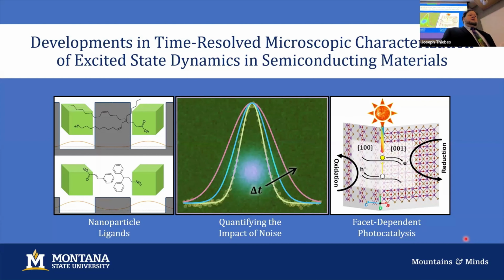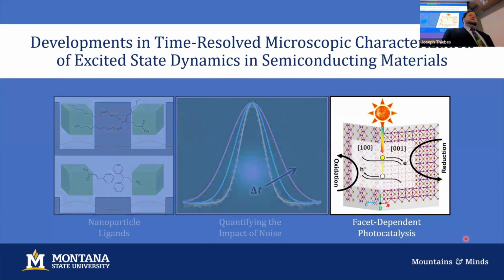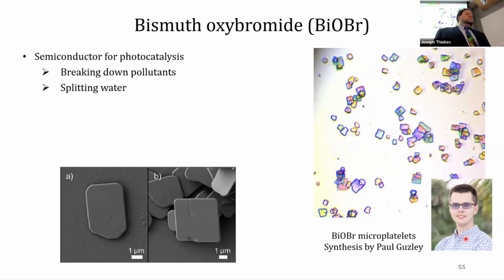So that brings me to my third topic, which is the facet-dependent photocatalysis that we see in this new photocatalyst material, the bismuth oxyhalides. In particular, the one that we look at is bismuth oxybromide. Paul Guzley helped us, and he synthesized these and did this SEM, did a terrific job. You see, these are also colorful. This is actually thin film interference that we see in the visible light microscope. It's like oil on water, where you see the rainbow colors because it's such a thin film. It's the same thing happening here. You have these very thin, flat platelet crystals that interfere with the light, and depending on how thick the crystal is, you get different colors. If you just look at them in a pile on the table, they're white. But they're kind of cool like this.